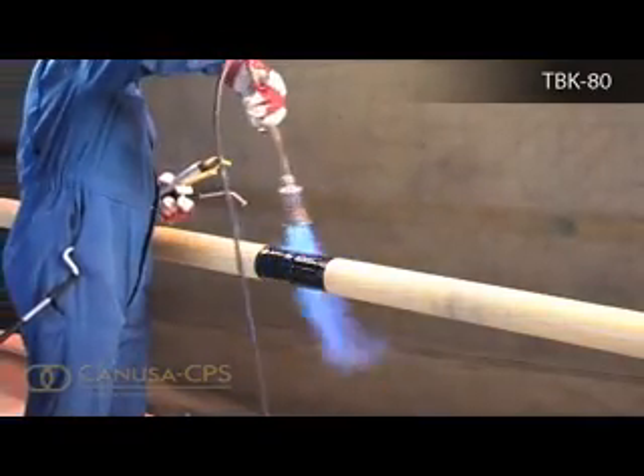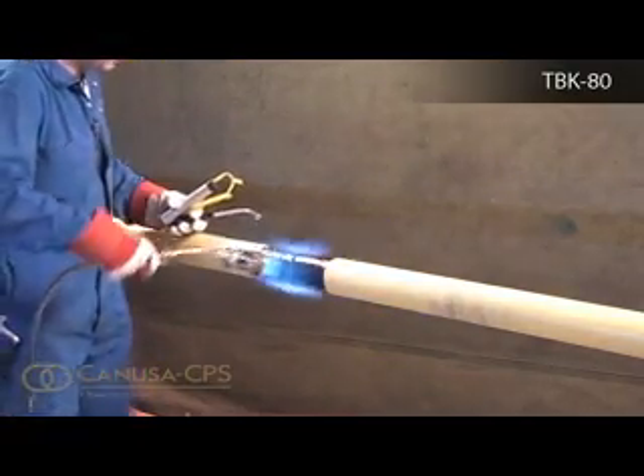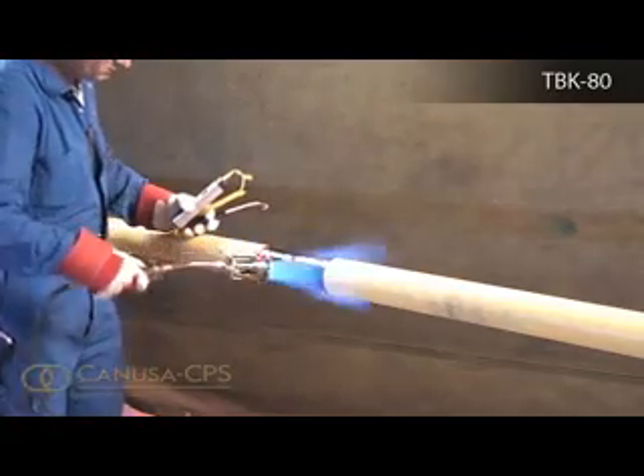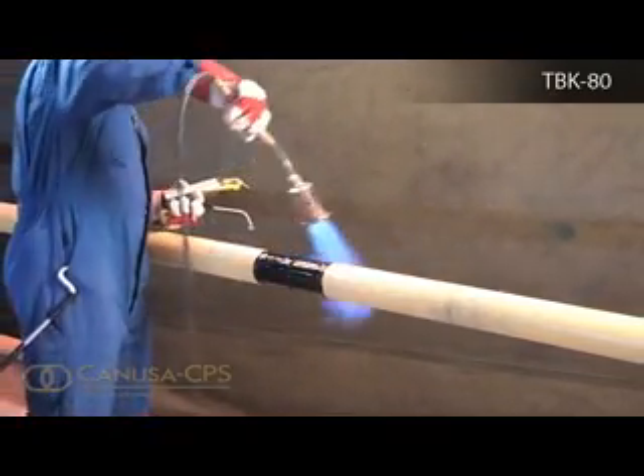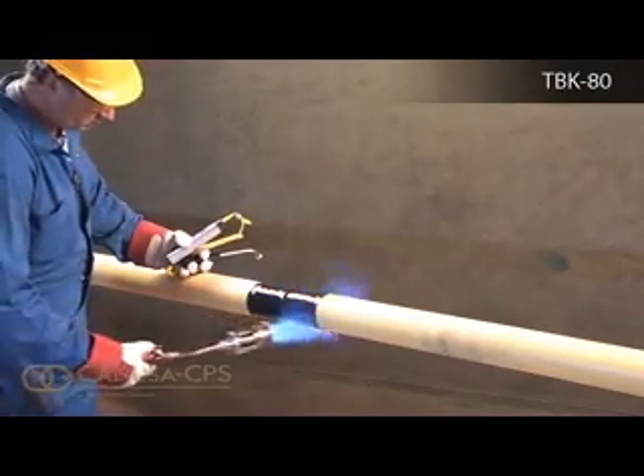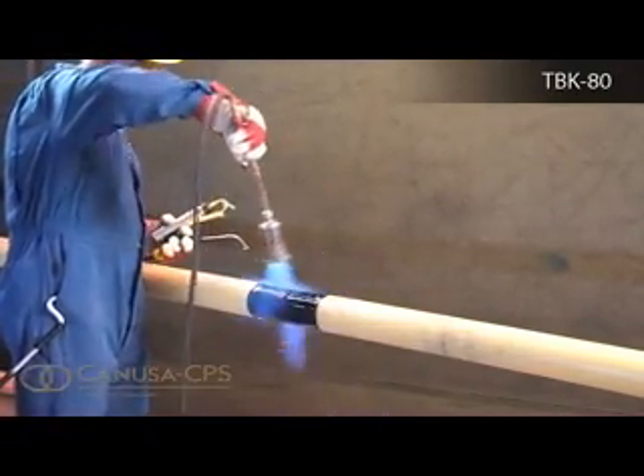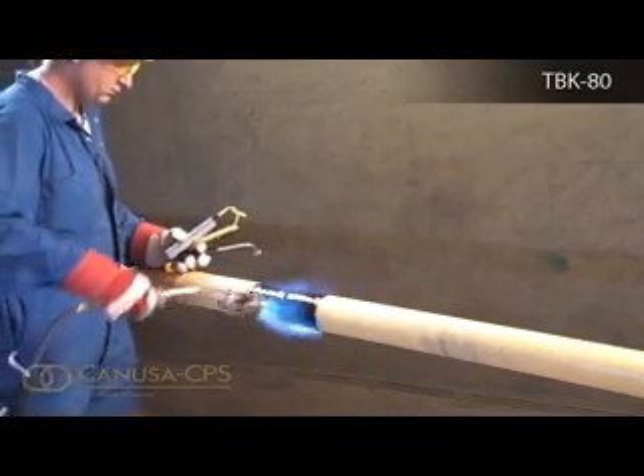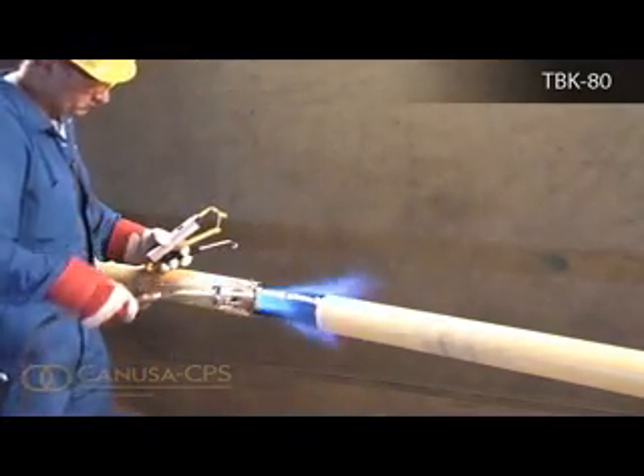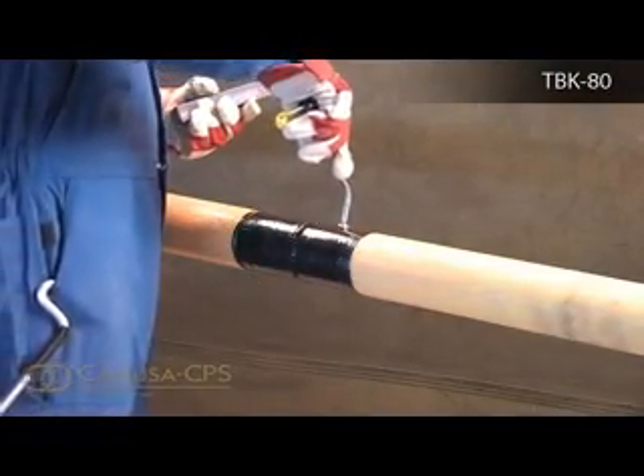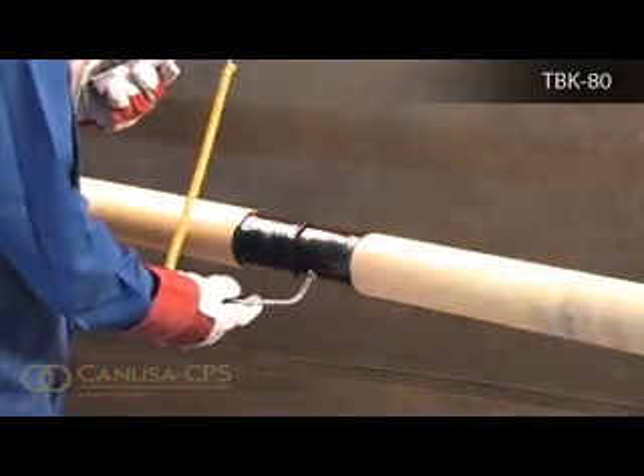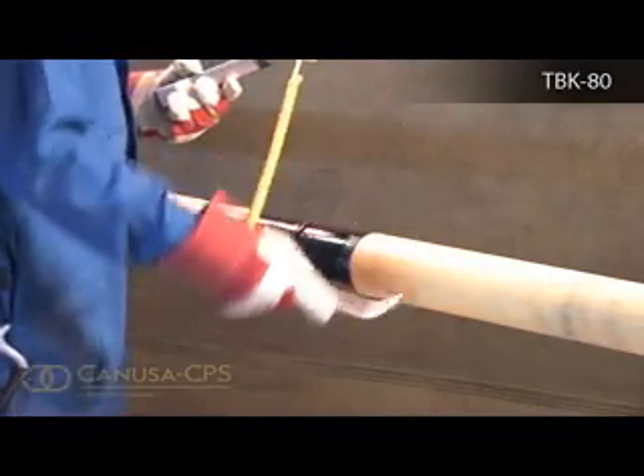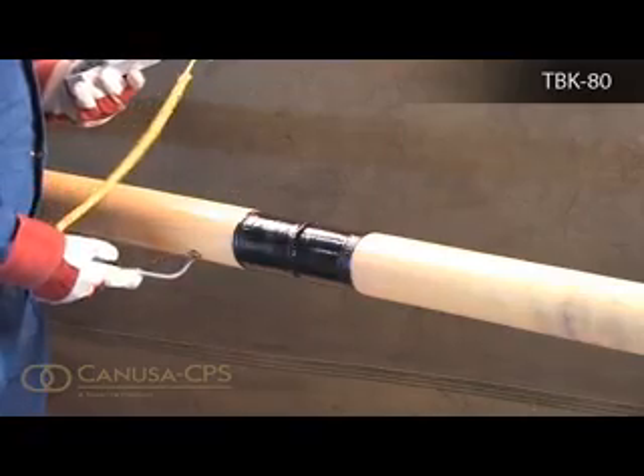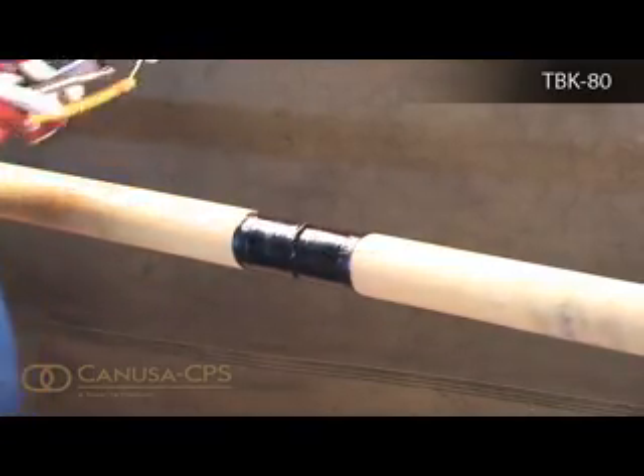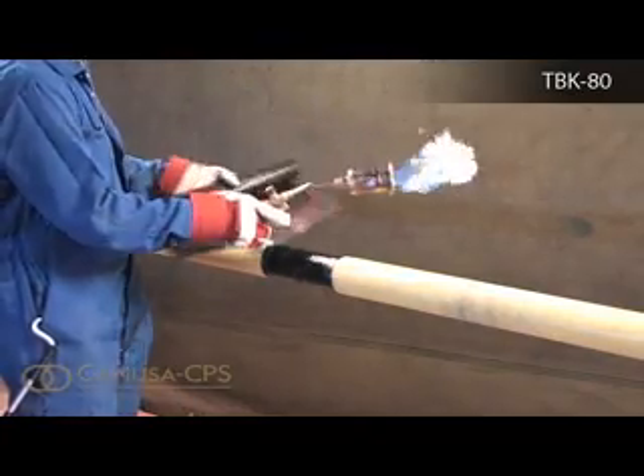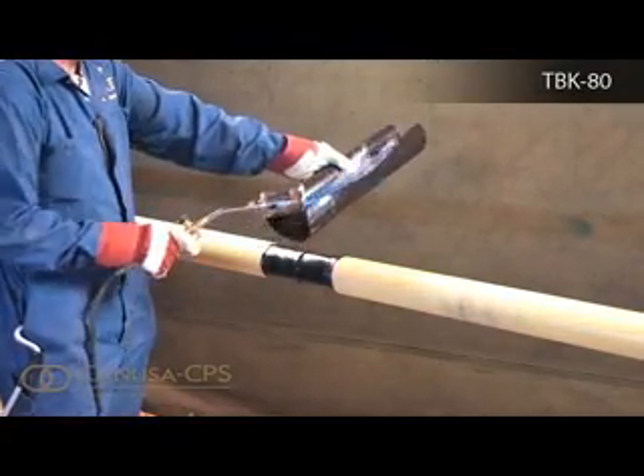Using the appropriate propane torch, induction heating, or infrared heating equipment, preheat the applied epoxy primer to the required temperature as indicated in the product installation guide. Do not use an intense flame on the mainline coating, and if a film develops on the coating because of overheating, use a surface abrasion tool to remove it. Check the temperature to ensure that the preheat temperature has been obtained on the entire pipe circumference. This preheating will substantially cure the epoxy and ensure proper flow and bonding of the sleeve adhesive. Ensure that the epoxy primer is dry to the touch prior to sleeve installation.